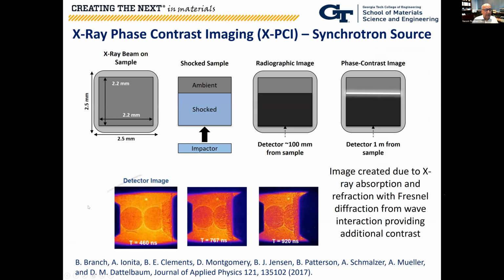Just to give you a simple understanding of X-ray phase contrast imaging, suppose you have a region of a sample that you're subjecting to an X-ray beam, and suppose part of that sample is shocked by shooting an impactor on it. So part of it is shocked, and the remaining part is at ambient condition. Remember, the shock state is where the high pressure is moving as a front. Ahead of the front, the material is in an ambient condition, and behind it, it's in a high energy, high pressure state, and there is a sharp interface because there is a significant density difference.